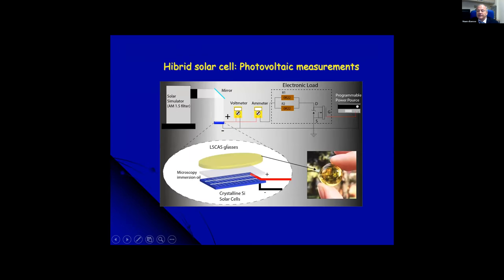This is the way we are putting the sample on this silicon solar cell, and then the coupling, we call it a hybrid solar cell. It's a photovoltaic measurement, and this is just for you to understand what the application of this system could be. Of course, there is another advantage, because when you use this kind of doping in glass, the glass itself would block the UV radiation that is known to be very important in degrading the silicon solar cell. So the glass could work as a sensitizer for the downconversion process, and at the same time could be used to protect the solar panel against degradation from UV radiation.